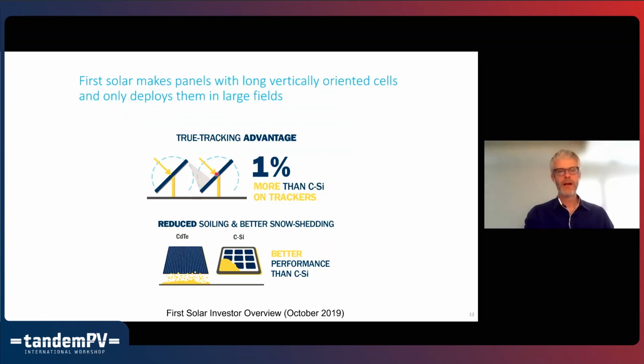To some extent, I'll say silicon panels avoid the problem by having bypass diodes, and they break the panel up into typically 4 strings. And if one string has a shaded cell, then that will get shut down, and the other strings can still generate power. And with cadmium telluride, they do have the problem. In other words, the cells do get damaged, but you would need a bypass diode for each solar cell, and it's too expensive. And so I don't think First Solar does it.